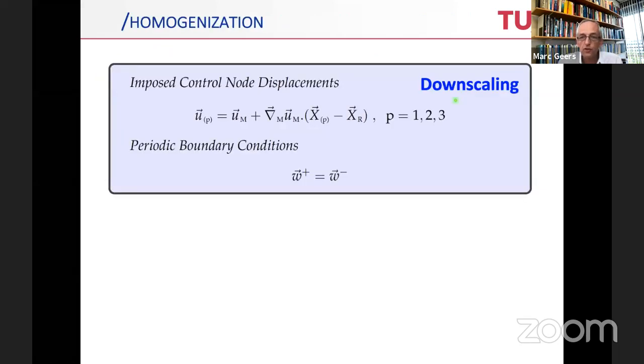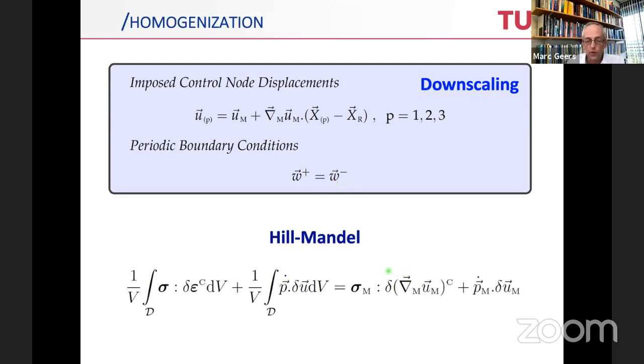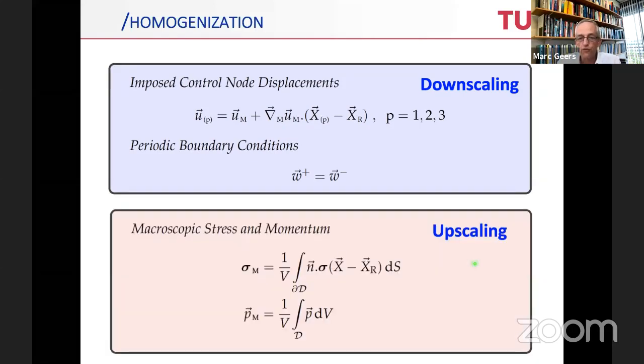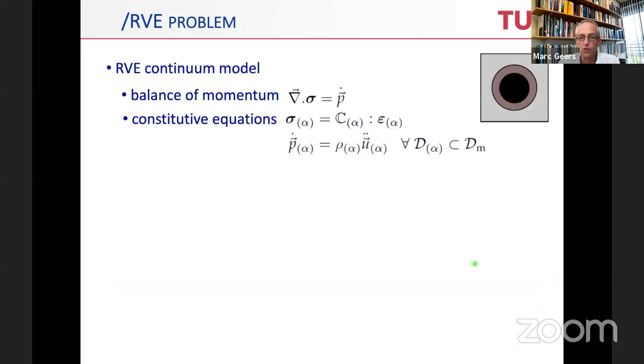So how does this work? A little bit of machinery that is very similar to what is used in computational homogenization. First, the downscaling relations, where you downscale the macroscopic displacement to the level of a representative volume element with periodic boundary conditions. The Hill-Mandel lemma, which tells us that the average work at the microscale per unit of volume is equal to its macroscopic counterpart. And once you have made these two assumptions, the upscaling relation follows, which is the average relation for the stress and the momentum. That's an equation that just comes out once you have adopted the Hill-Mandel condition.